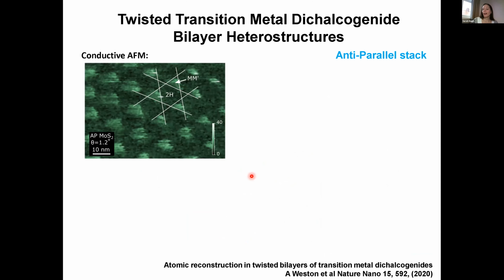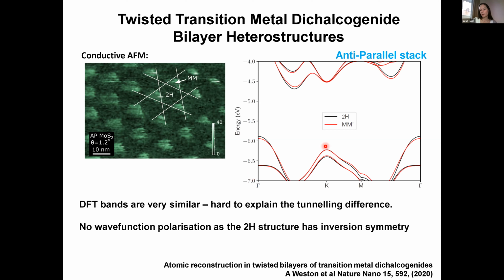Okay, so then we started to look at the anti-parallel stacks. Those were the ones where we had the hexagons and also the little triangles. And here we were really surprised because we found that the type stacking really lit up in the conductive atomic force microscopy. And that led all of us really to scratch our heads for quite some time to try and understand that. It's not the same effect of these differences in the electronic structure. In fact, the electronic structure that we get here is very similar for those two domains. That doesn't explain what we get in terms of the differences in the tunneling current.